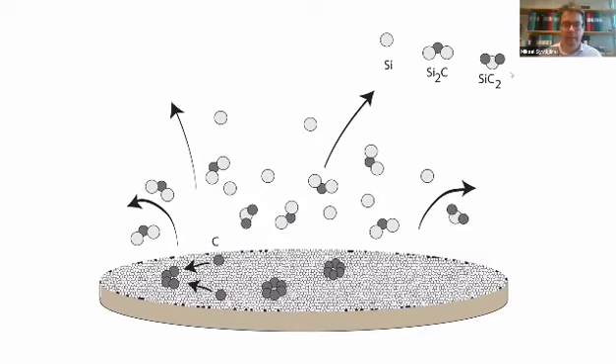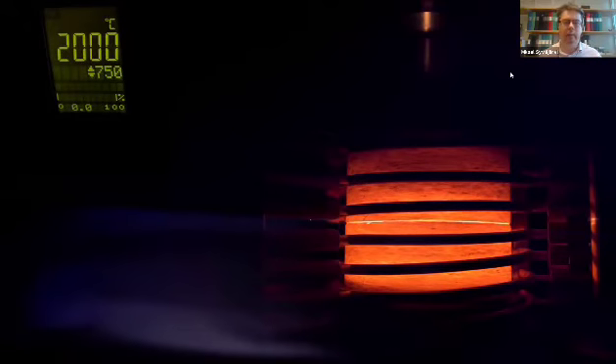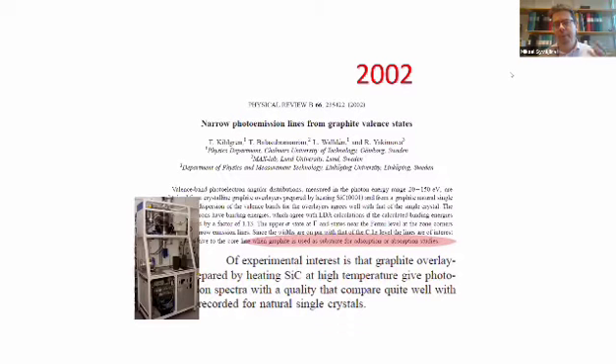We have been developing this for quite many years, and around 2000 degrees C is one of the secret temperatures for this process. But actually, when we were heating up silicon carbide, we got this graphitization, which was not desired. Then in a collaboration with Chalmers University of Technology, they requested such graphitized silicon carbide to study it intentionally. And as growers, we were a little bit hesitant to do this intentionally. But then it was found out that the graphite on silicon carbide has very high quality.